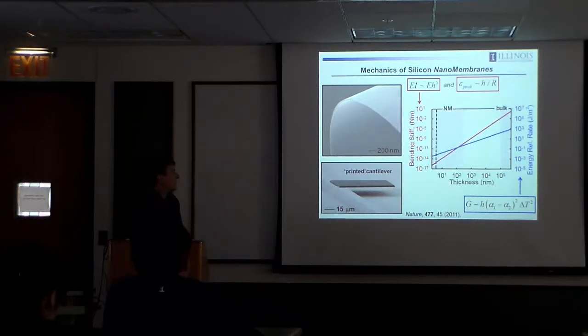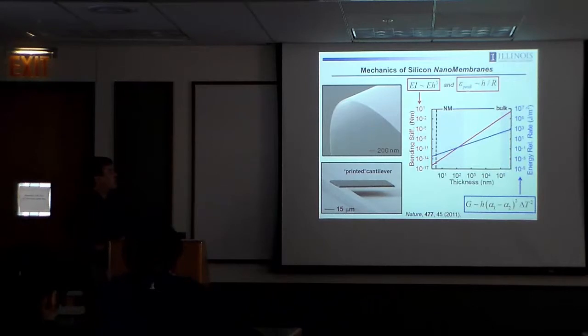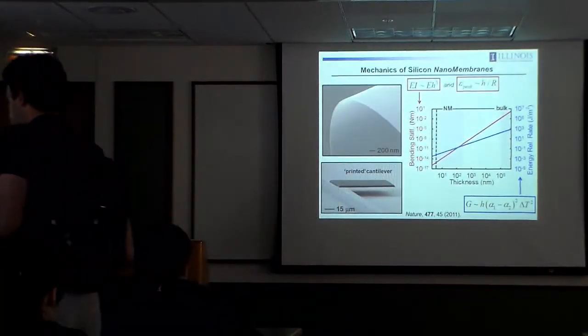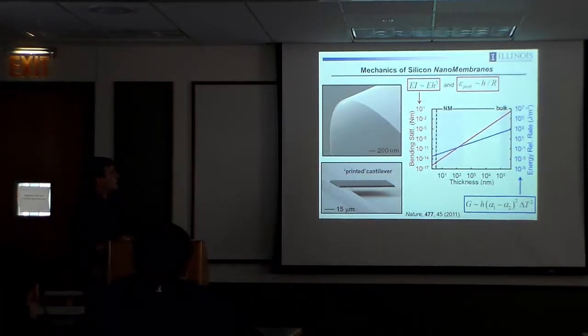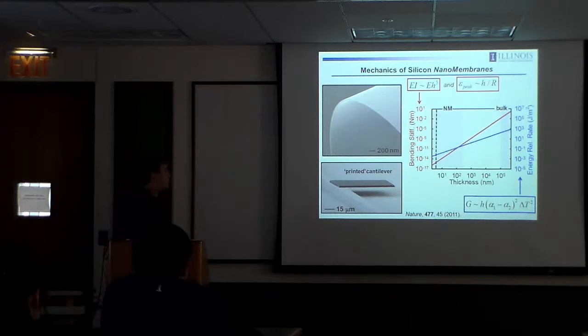And you can see it here. This is a 20 nanometer thick sheet of monocrystalline silicon. So that's sort of interesting. The other consequence of small thickness is that for a given bend radius, the peak strains induced in the material scale down linearly with thickness. So R is the radius of curvature, h is the thickness again. So not only does the material become floppy in the sense of a very, very tiny bending stiffness, but it also becomes very flexible. You can bend it to a very tight radius of curvature before you reach thresholds of strain that would crack the material. So those are useful things to think about.